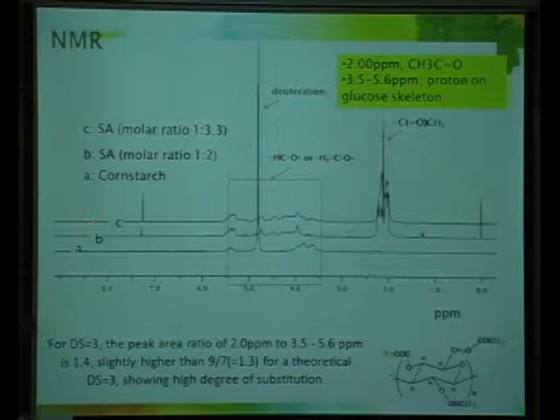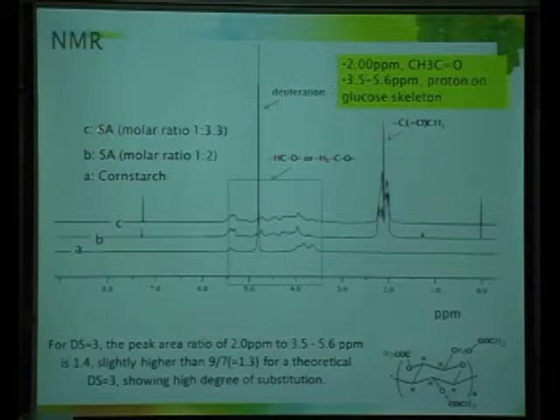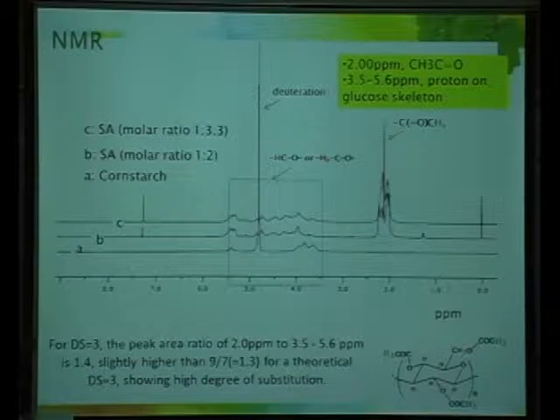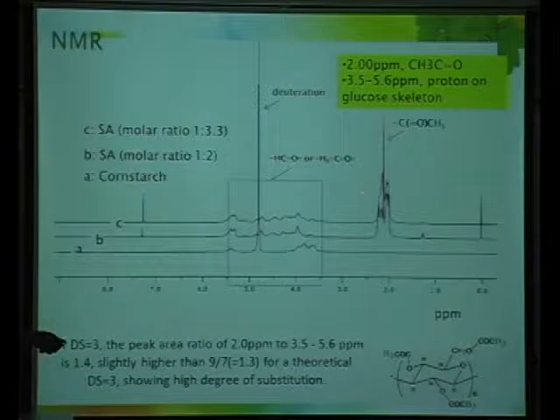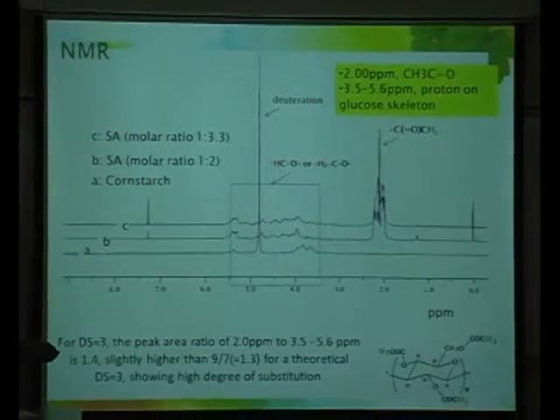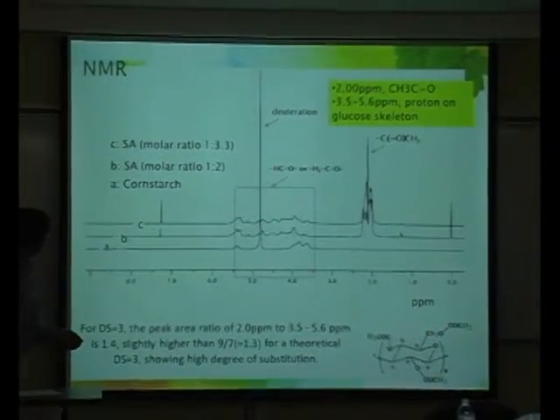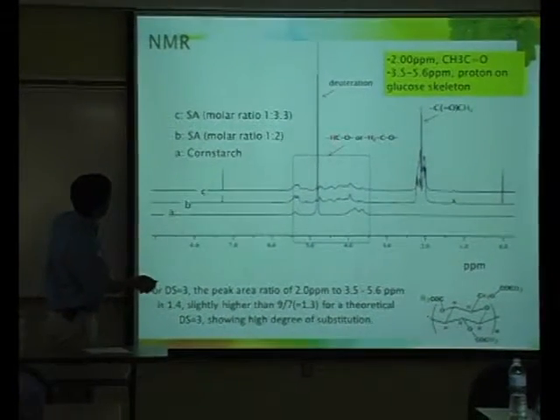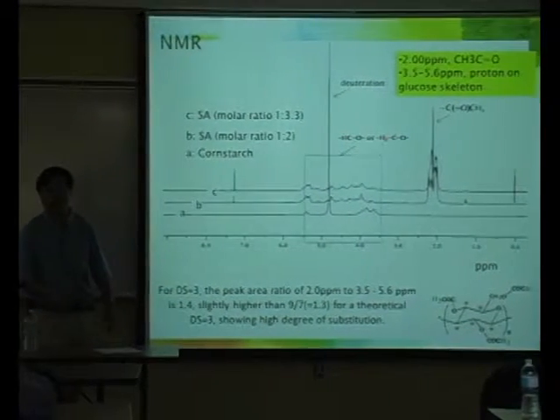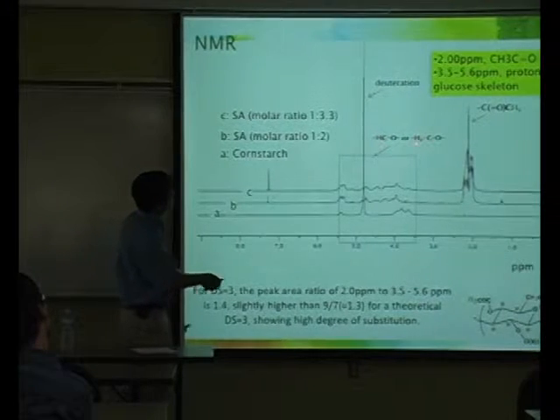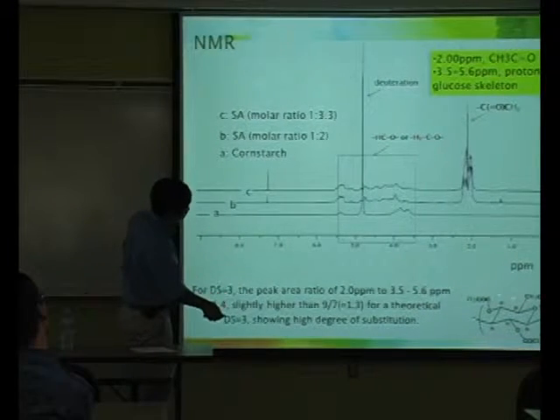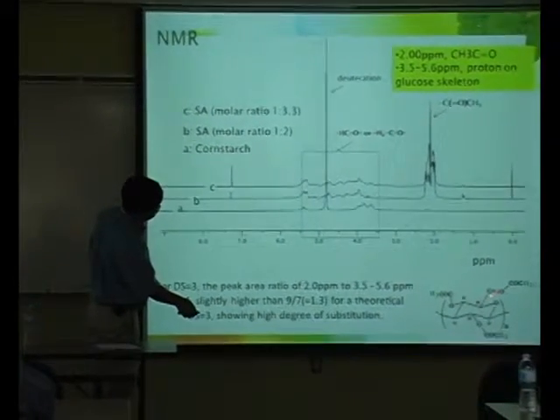And if you do the esterification, B and C actually have different substitution ratios. This is the 1:2 ratio, 1:3 ratio, so the degree of substitution is about 3 and 2. We can look here and calculate. This proton is this H on the ester group. And another functional group is shown between 3.5 and 5.5 here. Those are the H protons, because this is H NMR, so it only looks at protons. The proton here, the H2, is shown here. This is the ester group here.